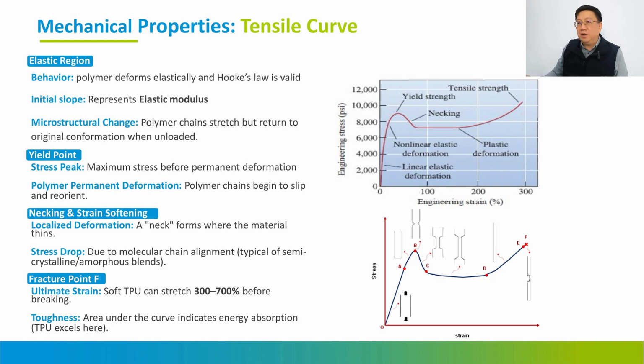You can see this curve. In the first movement, we call it the elastic region, which means the material is being stretched, and if it does not go over the yield strength point, as I mentioned earlier, it will come back to its original shape. We call this the hysteresis loss, which is very low. And the initial slope we call the elastic modulus. In a microscopic way, the polymer is being stretched, but it comes back to its original conformation when unloaded. So when you unload the aligner, it comes back to its original shape.